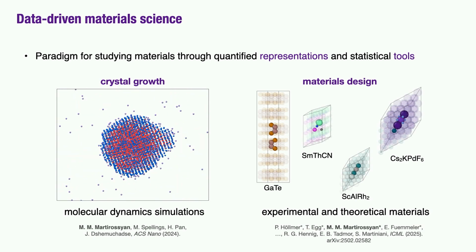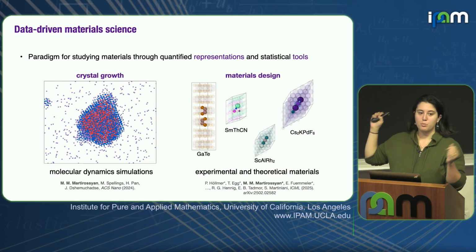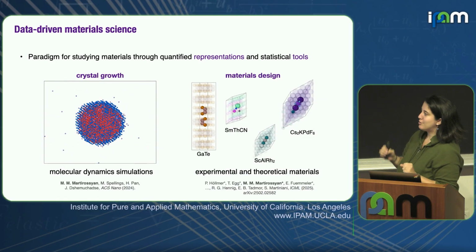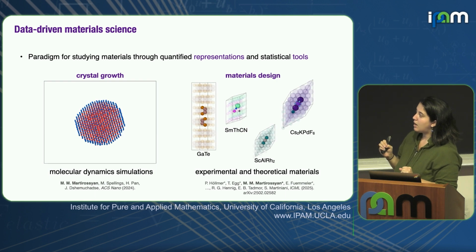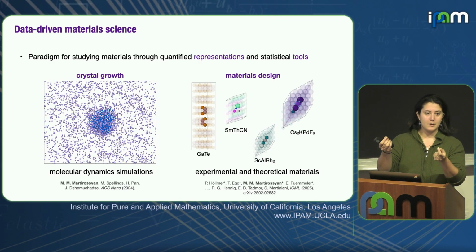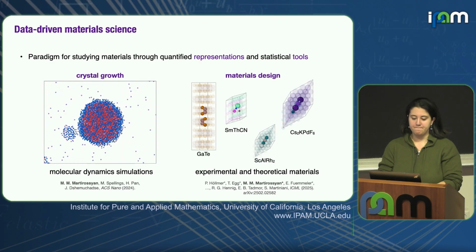How do you get a crystal to form on an MD time scale? You use a very special class of potentials, which are pair potentials, but they have multiple wells. In this case, the crystal that forms is BCC. There are probably parts of the Lennard-Jones phase space, by phase space I mean the phase space defined by the interaction, where there's probably something you could do to a Lennard-Jones to get it to form BCC, but in this particular case, it's a pair potential that has two wells. No real barrier, just agglomerating.